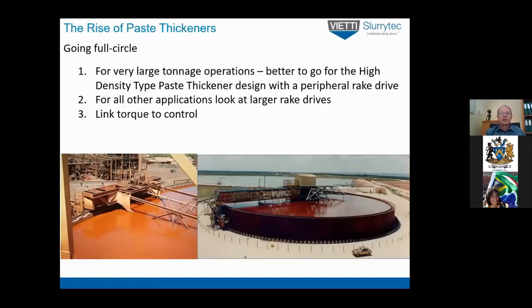So going full circle then, for very large tonnage operations, it's probably better to go for a high-density paste thickener design with a peripheral rake drive, like was done in the early days. And you have to go through these lessons, learn your lessons, and then look back and say, oh well, the guys did have a good idea in the old days. For smaller applications where you don't need such large diameter paste thickeners, then probably look at larger central rake drives with higher rake torques. And then obviously link torque to control, because that was probably the best control method you can go on.